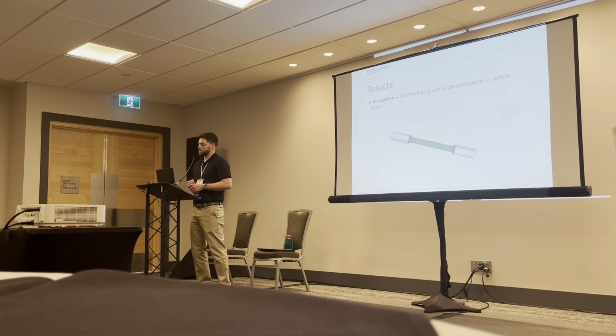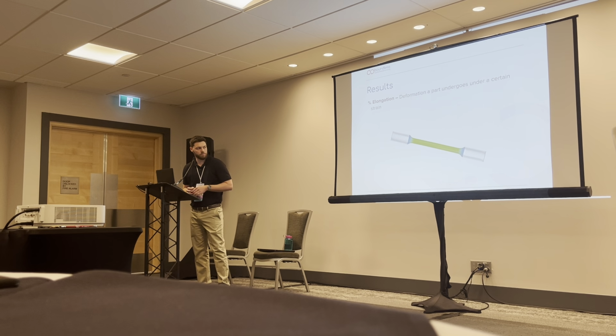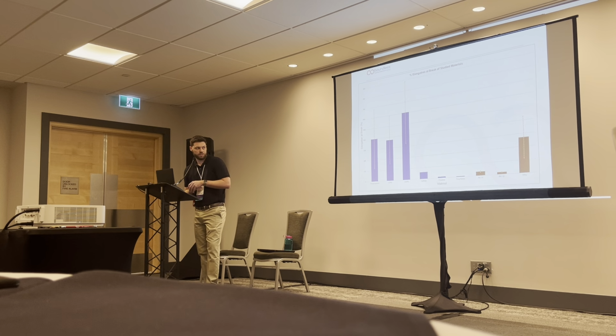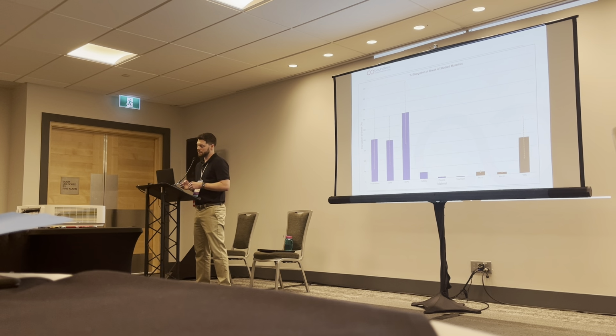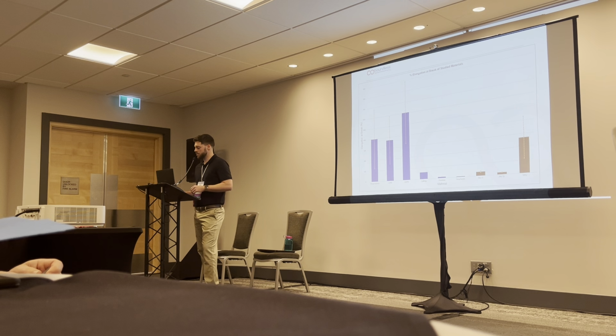So the first property we looked at was percent elongation, or the ductility of the material, and that is measured by a tensile test and measuring the amount of deformation that the material has undergone. For each of these graphs, the blue bars represent the traditional thermoplastics, the gray bars represent the 3D printed materials, and the orange dotted line is the standard deviation between the values that we found. So the first property, percent elongation or ductility. What we found was that PA11 was very comparable to the copolymer, whereas PA12 was very comparable to the ProComp material. And then lastly, the TPU had similar properties to the low density polyethylene in terms of how ductile the material is.